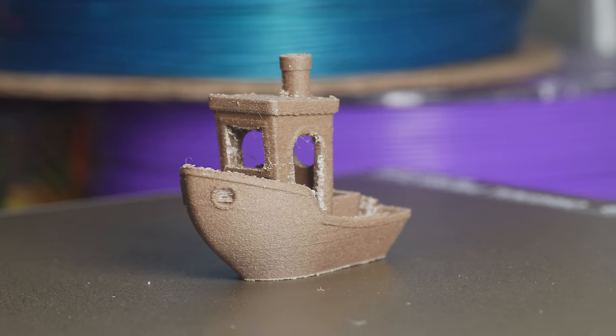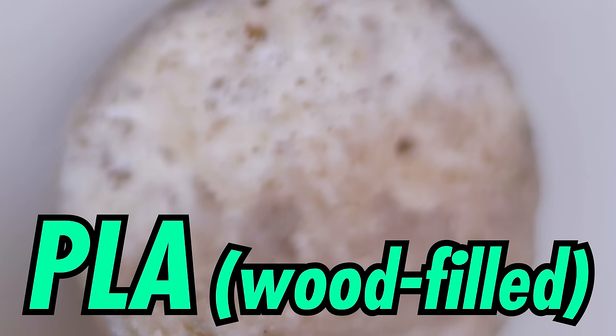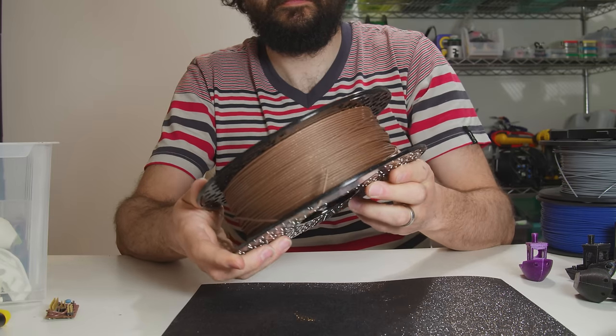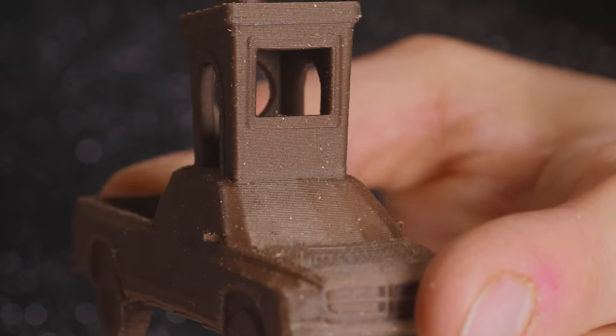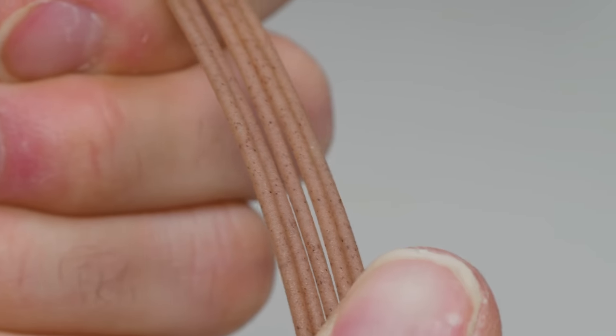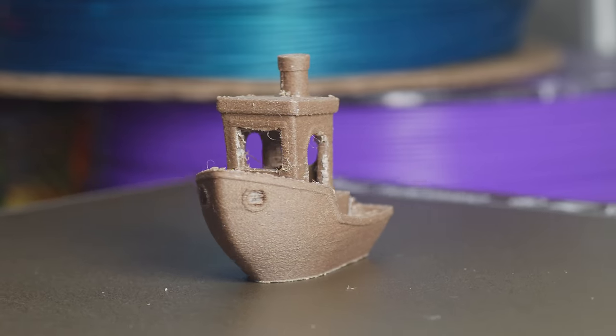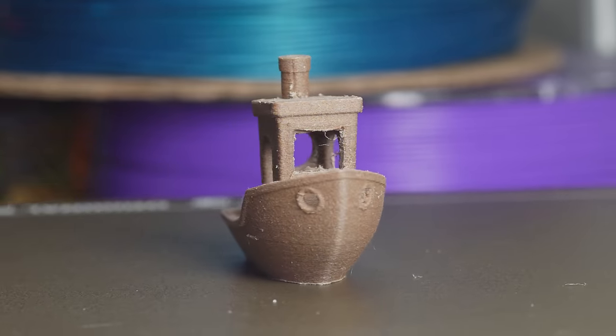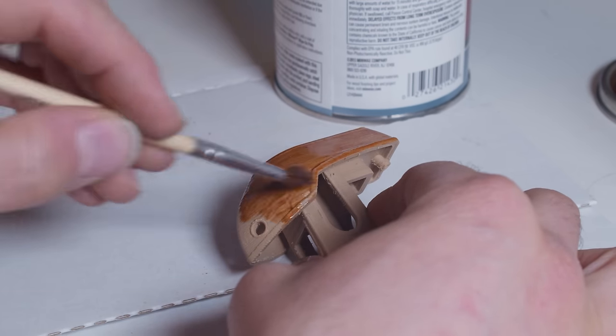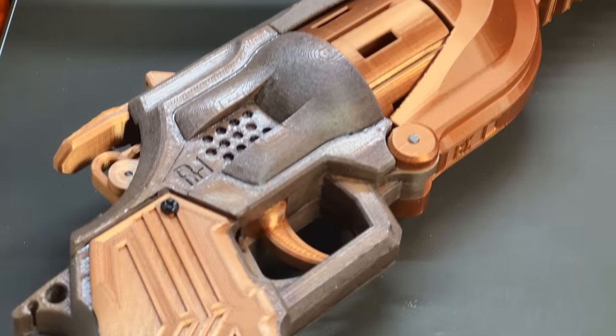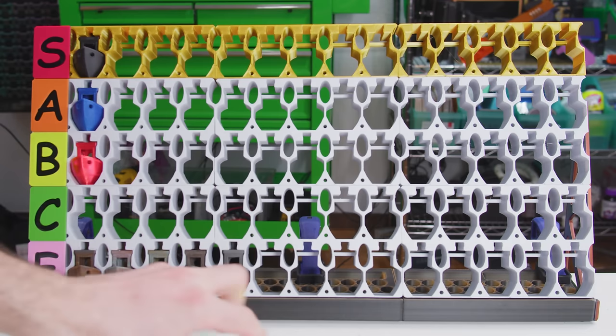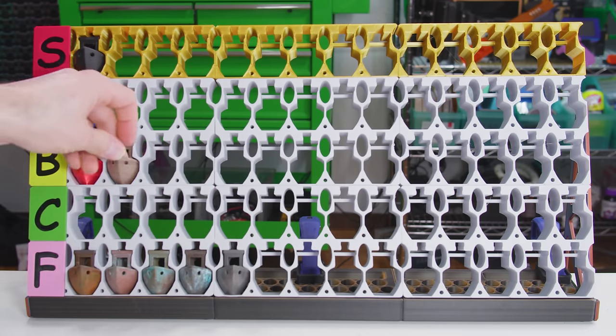Our next filament is even less useful, but it's way more charming. Wood PLA. This is plastic plus sawdust, and your mileage will vary. Crappy wood PLA has such finely-powdered plant product, it's just regular PLA, but brown, and worse. Quality wood PLA has visible chips, and that's the kind I'm talking about here. Wood PLA is not very pleasant to print, it spurts and sputters, especially after absorbing humidity, which it does very easily. The end product is also a lot weaker, but the soft, springy surface really does feel like hardwood, and while it doesn't really look the part, if you hit it with some varnish, the wood grain effect is surprisingly convincing. The lower quality the print, the more convincing the effect. I'm gonna put wood PLA in B tier, B for bamboo, which is the most common wood in wood filament, even though it's a grass, false advertising.